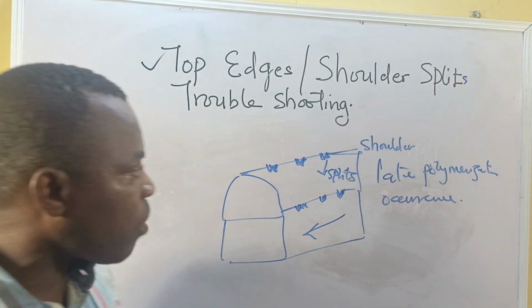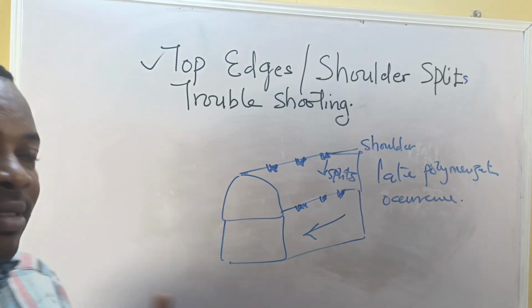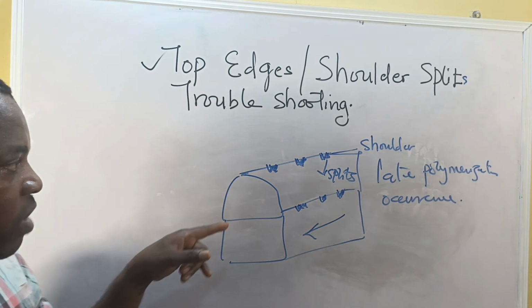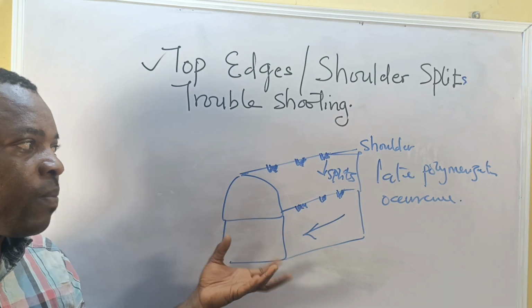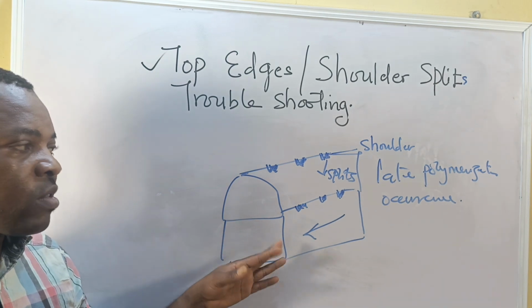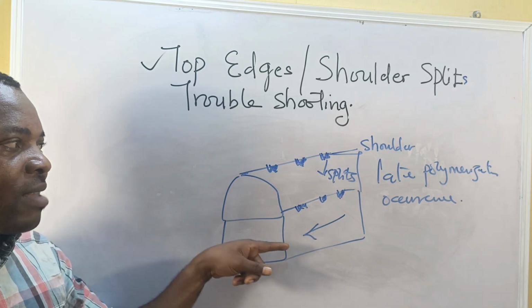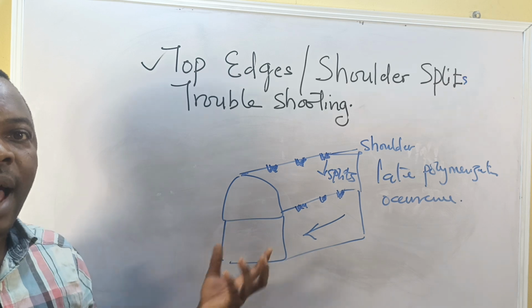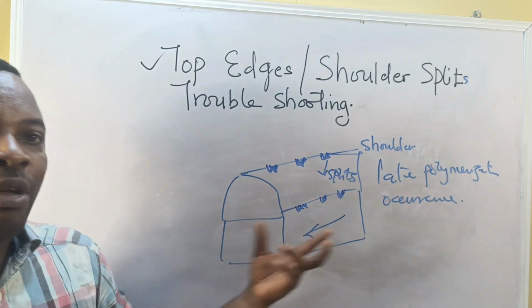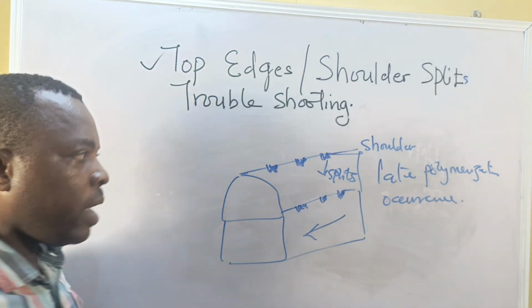There are several factors that could lead to this: the temperature and the use of your tin catalyst in that reaction. Because the tin catalyst here is not sufficient. It could be sufficient, but because the temperature is a bit cooler, it will counteract the strength of that particular formulation that you were using, making it seem insufficient as a result of temperature. So it will make this polymerization occur late.